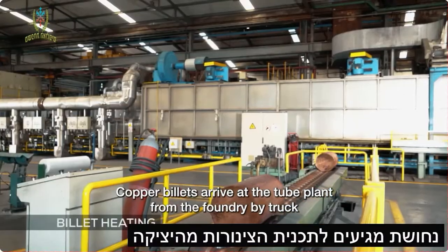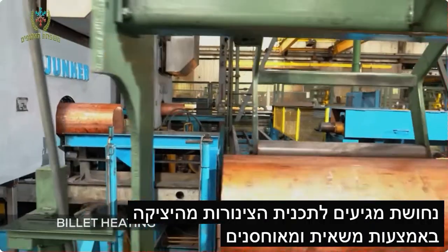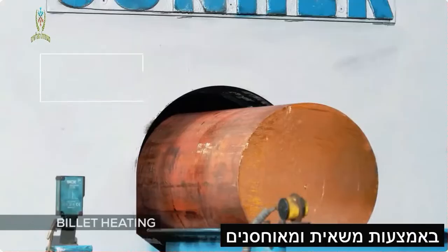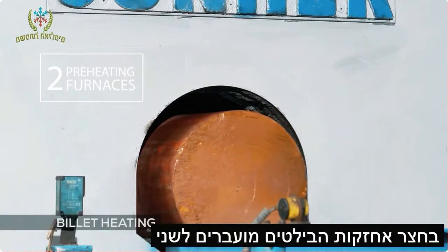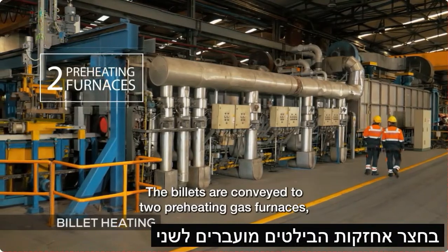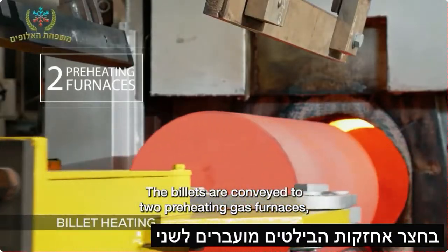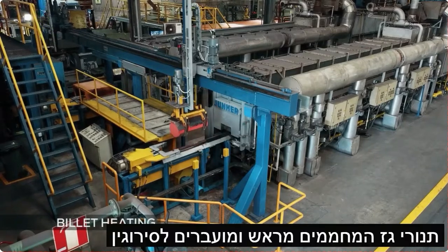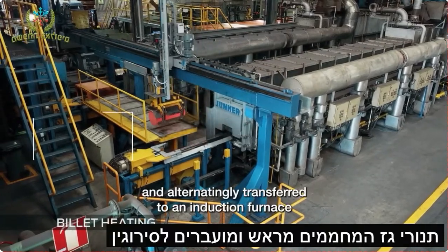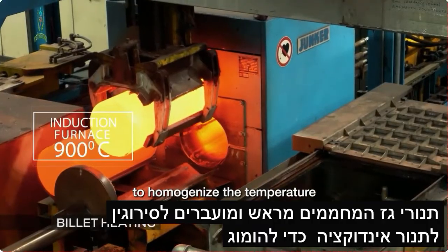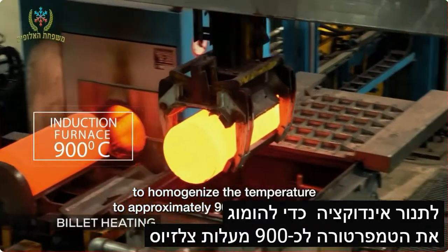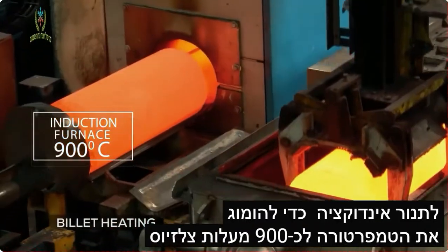Copper billets arrive at the tube plant from the foundry by truck, and are stored in a holding yard. The billets are conveyed to two preheating gas furnaces, and alternatingly transferred to an induction furnace, to homogenize the temperature to approximately 900 degrees Celsius.